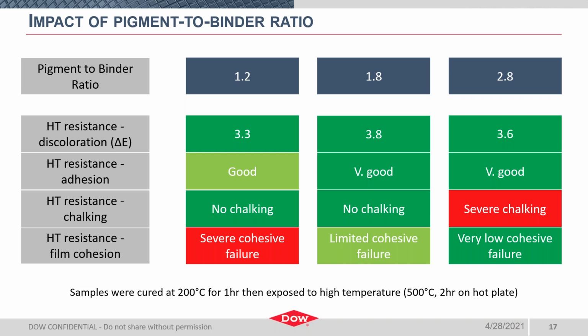So what this does is give us a good idea of how we can tailor that pigment loading to tweak performance. Hence, while the recommended pigment to binder ratio is going to depend on the desired performance, in general, 35% binder in the dry paint, or in this case, 1.8 pigment to binder ratio, did maximize the overall coating performance, including that adhesion to cold rolled steel.